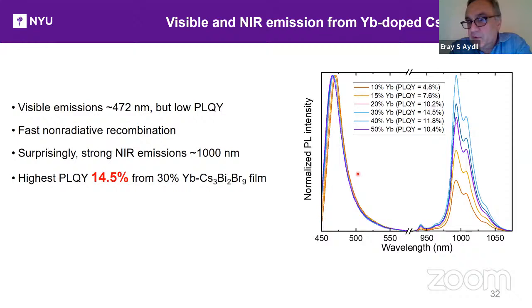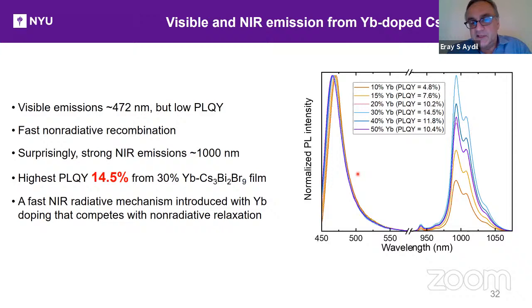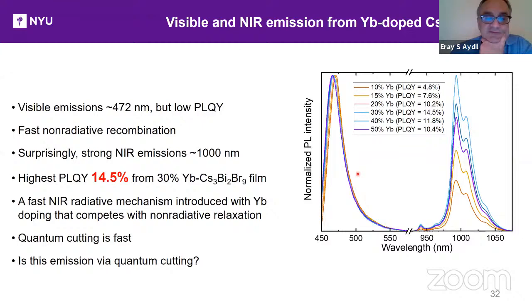So something really fast is able to compete with non-radiative recombination. And so this radiative mechanism is introduced with ytterbium, and it competes with the non-radiative relaxation. One thing that I didn't say is that the quantum cutting in cesium lead chloride is very fast. So this is an encouraging sign. It's not over 100%, but certainly by putting ytterbium in there, we have a fast energy transfer mechanism. Is this emission via quantum cutting? A question.